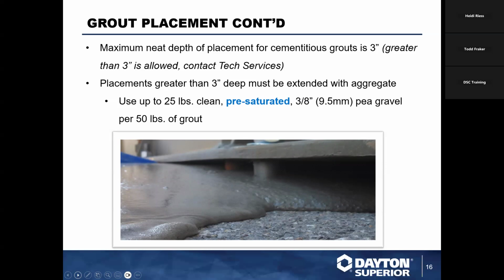I have approved grout placements as deep as 8 feet deep in an annular space, which is the distance between the metal, say they're grouting in a metal lining inside of a concrete tube. That annular space can exceed 5 inches, 8 feet deep, but you've got a lot of substrate to dissipate the heat off the grout. So there's lots of geometries, if you will. So the 3 inches are in the data sheet, but I will say this, if you give us a call or a customer calls us, we will walk through it and decide whether or not it makes sense.